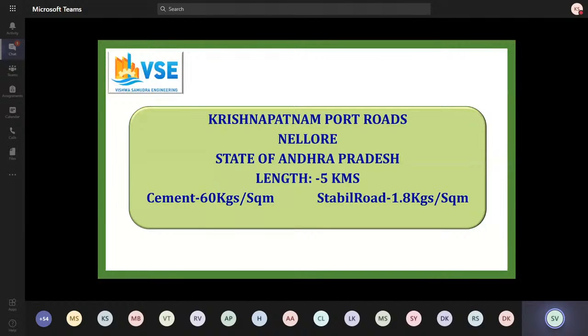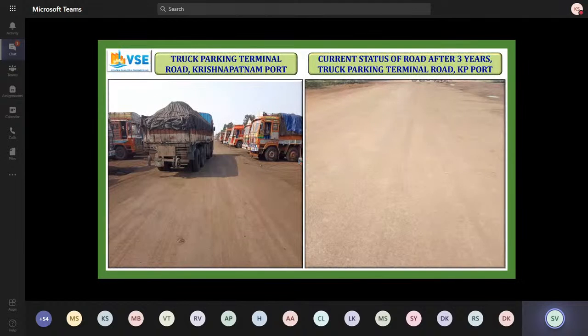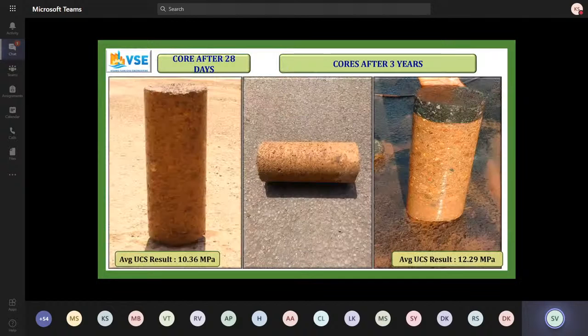Just happy to say that in 3 years, not a single rupee has been spent on maintenance of these roads. You can check with the port authorities as well. It's holding up very well. These are the roads after 3 years. This is the core. On the left is after 28 days. On the right is after 3 years. If you see, it's exactly the same. This is a greenfield road. Not one single aggregate have we used on these roads. No DBM. We went straight for BC because we also wanted to test how it performs, and it's absolutely fine. There's only a layer of BC on top.